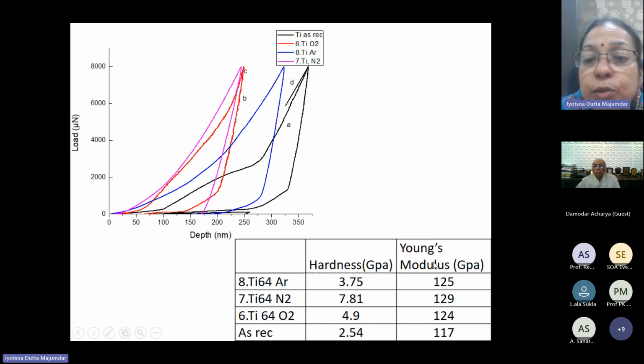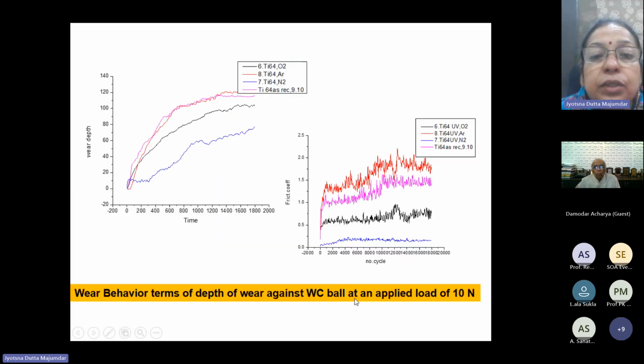If you see, the Young's modulus was significantly a little bit higher than that of the substrate because of presence of oxides, nitrides, dissolved phases, and hardness was also improved to a large extent because of oxide and nitride phases on the surface. Due to all these things, there is improvement of wear resistance property. These are dry wear results which we observed long back.